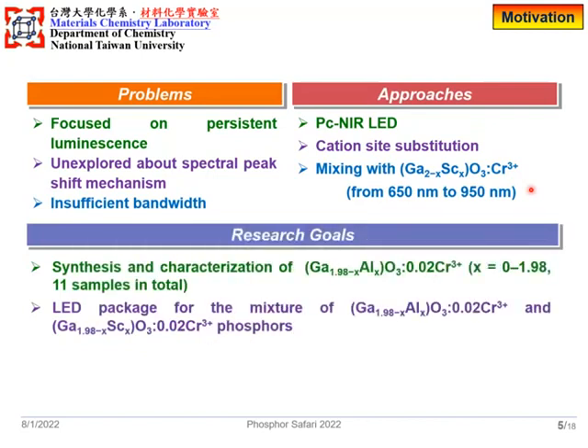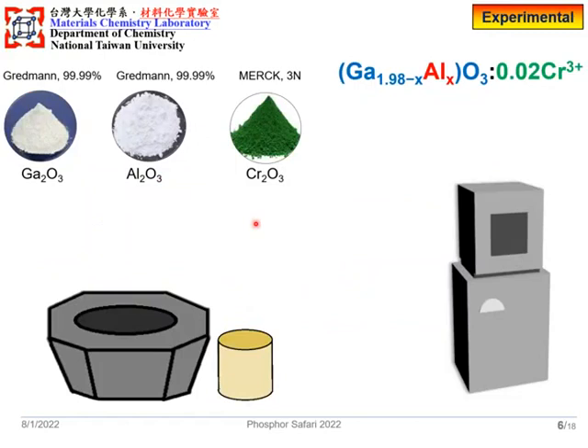Our research goal is synthesis and characterization of gallium oxide doping with different concentrations of aluminum. And we also do the LED package for the mixture of our phosphor and the gallium oxide doping with scandium. Here is the experimental part.